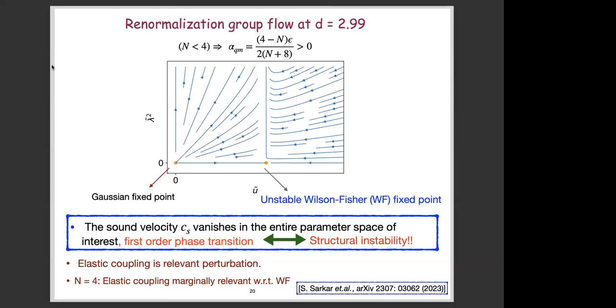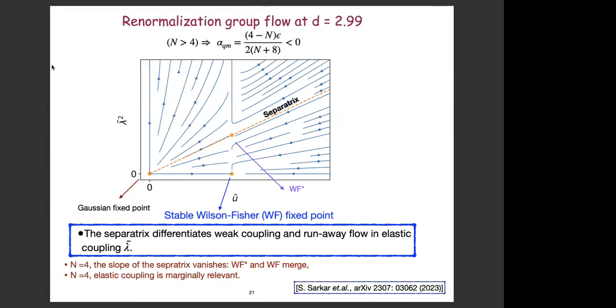And sound velocity is in turn proportional to the elastic constant of the system. So that means the elastic constant of the system vanishes, which indicates a structural instability or first order transition in the system. So that is good that, at least for this quantum critical system also, for alpha quantum greater than 0, we can have a first order transition similar to the classical critical system. And the elastic coupling is relevant, as we can see from this flow. And if we go to the n equals 4 limit, the elastic coupling becomes marginally relevant with respect to the Wilson-Fisher fixed point. Okay, so next we come to n greater than 4, that is alpha is less than 0.